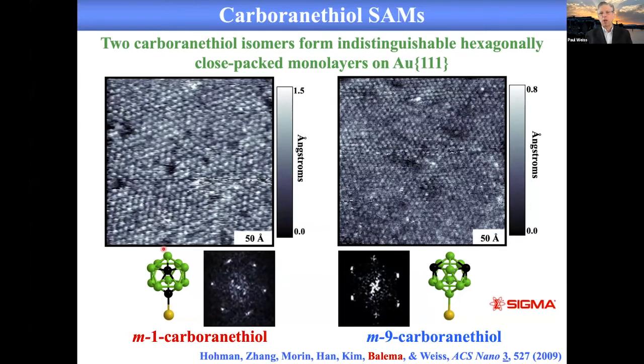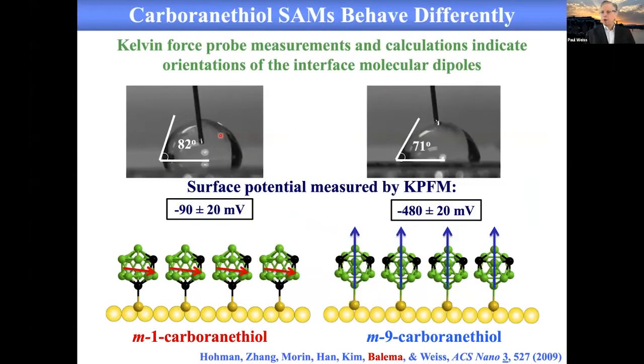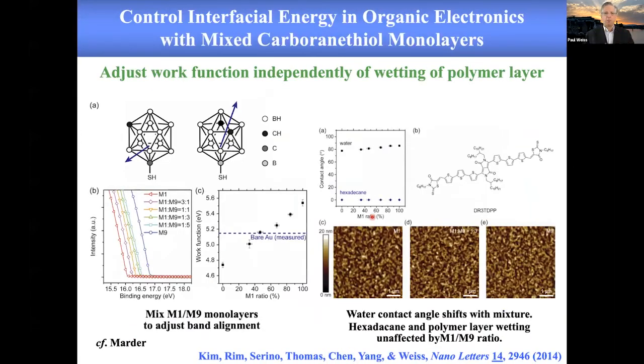And so Jay Kim in my group took that idea and he said, well, one of the problems with organic electronics is how do we get good alignment between the bands of the contact and the bands of the active material? And so people like Seth Marder will put a polymer interlayer, they'll fluorinate it, and then that'll add negative charge. And that's the way that people have done the band alignment. But the problem with fluorinating a polymer is that's basically making that layer into something like Teflon and changing the wetting properties of the active layer. And if you change the amount of fluorine you put in, you'll change the wetting.